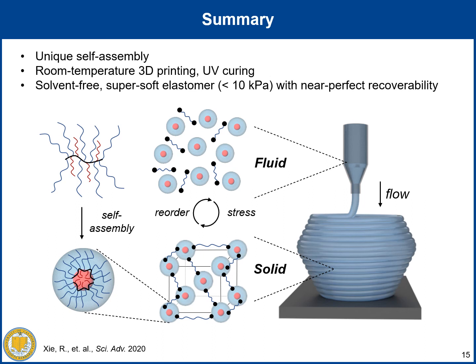Then, upon UV irradiation, the as-printed part can be transformed from a soft solid to a super soft, solvent-free elastomer with modulus of less than 10 kilopascal and with a near perfect recoverability above yielding.